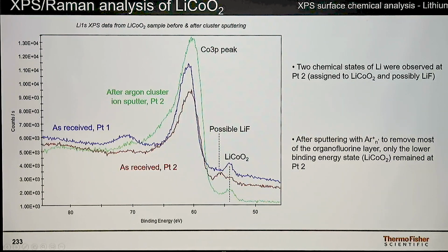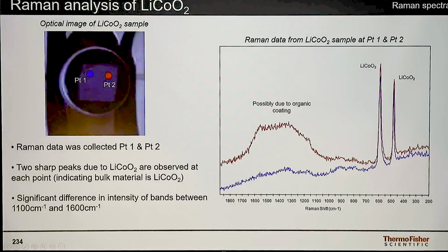And we could clean it up using the cluster source, and see whether that actually changes the chemistry we're seeing, looking really down for the lithium down here. And so we can see lithium cobalt oxide in point 2 after sputtering and point 1 as received. And in the as received point 2, we're seeing quite a bit of lithium fluoride present there as well. And in the Raman at points 1 and 2, that organic coating again. So it looked like from the XPS spectrum, it was due to an excess of that fluorine binder. And if we compare the Raman from the 2 points, it also suggests that's the case, that this big mess of stuff here is less present in point 1 than it is in point 2.